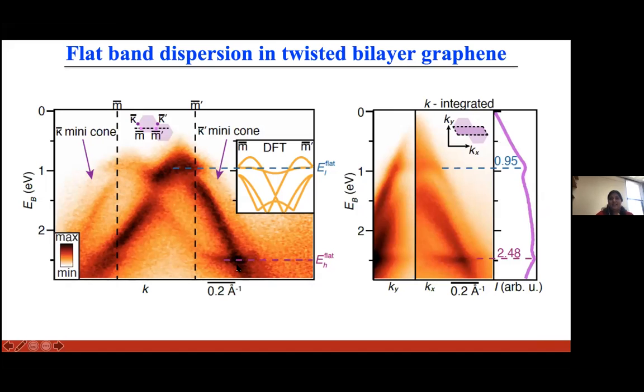And actually, you can see this much more clearly if we integrate the photoemission intensity in the two orthogonal directions of the mini Brillouin zone. And this is what I'm showing here. And so you can actually see the peaks due to the flat bands here and here.